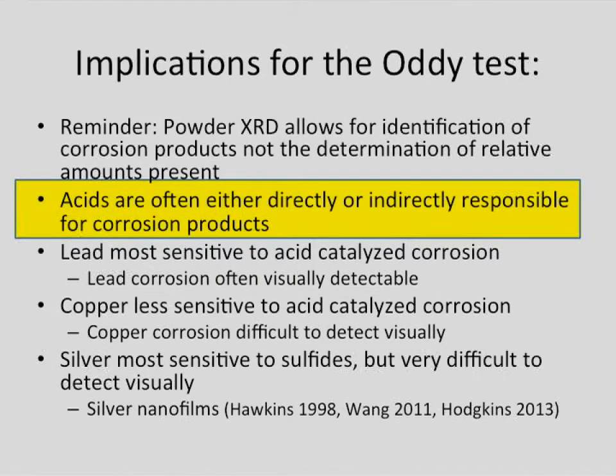And so what does this mean for the Oddy test? Primarily, remember that XRD doesn't tell us how much of any of these materials are there. It just says that they are there. So we can't use that as a way of differentiating or taking the subjectivity away from the Oddy test, but it tells us what's on the surface and possibly what's causing the corrosion.